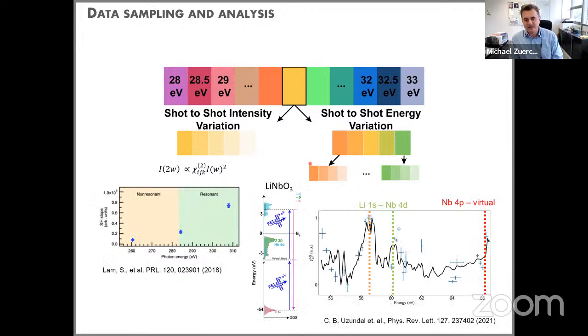And that is what we then did in our first experiment on lithium niobate. We basically used a much higher number of FEL shots to subsample the spectrum, first of all, to the bunches, to bandwidths in the range of a few hundred milli-electron volt per bin, and then use fine-grained tuning of the FEL to actually scan across a whole spectral range. And so that was our first work that we did in this area, where we studied lithium niobate.